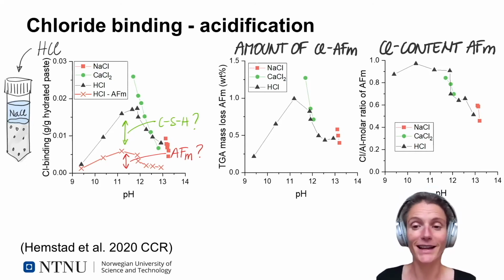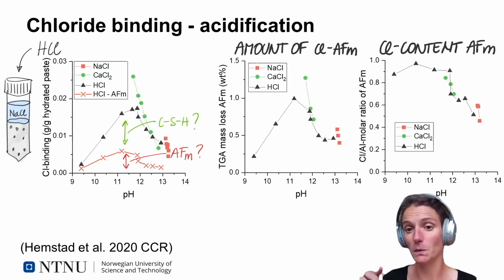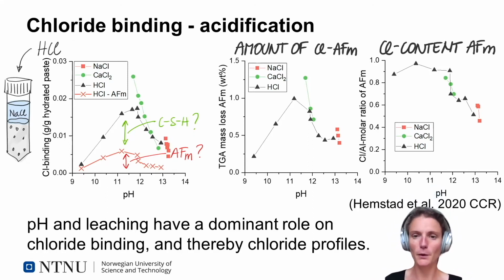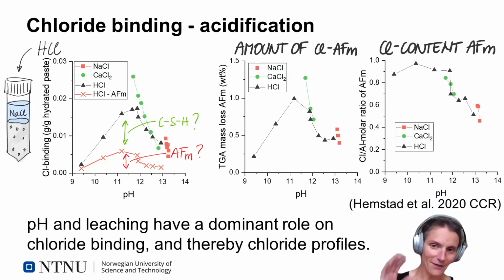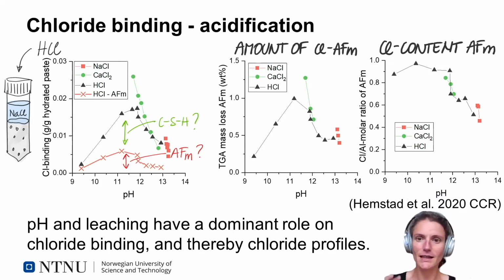Though this remains to be proven experimentally, and this is quite challenging because the CSH content will change and the composition will also change quite drastically in this experiment. So even though we haven't answered all questions, these results are very interesting and very relevant even for the engineer responsible for maintenance, because what we're seeing here explains something we see in the shape of chloride profiles.